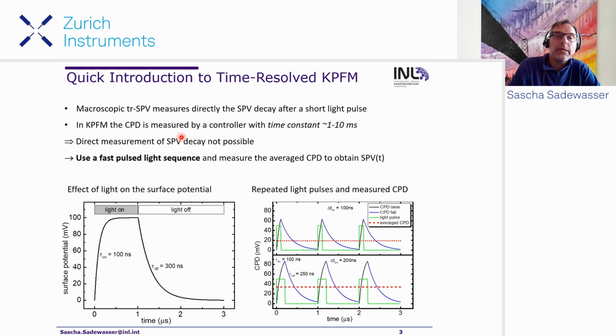In general, what you have to consider is that many of the charge dynamic effects in semiconductor devices happen at a fairly short time scale. So you can normally not resolve this in direct measurement as in many of the macroscopic methods, because your Kelvin controller, the CPD measurement, is happening normally on a fairly slow time scale in the range of milliseconds. So if you have a process that's in the range of hundreds of nanoseconds, as was just shown by Benjamin, then you cannot really resolve this in real time.